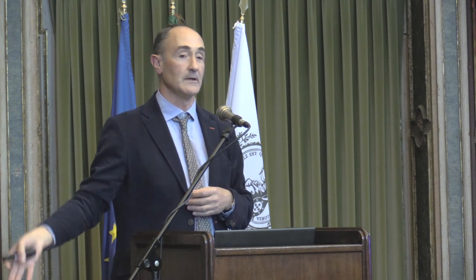Now, if we try to understand and to predict which will be the wavelength or the frequency of the oscillation of the electrons for particles of different morphologies, in principle, we have to resolve Maxwell's equations completely. And unfortunately, or maybe fortunately for the mathematicians, we can only do that by using numerical methods. So what we usually do is we take the particles that we want to simulate, we divide them in very tiny pieces that can be treated as a dipole, and then we apply the equations to calculate the interaction of light with that dipole, and then we integrate over the full volume of the particle or the assembly of particles. So now this can be done very efficiently nowadays, so we are really lucky that we can understand almost precisely how a specific particle will respond to irradiation of light.